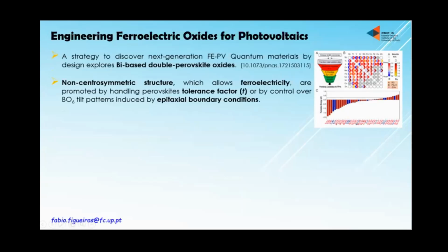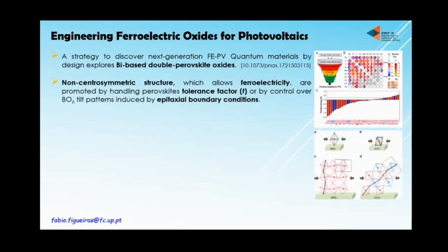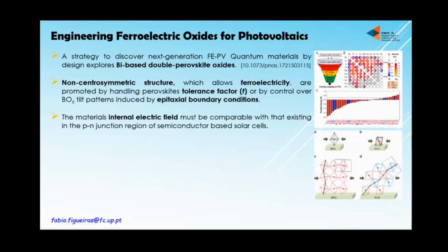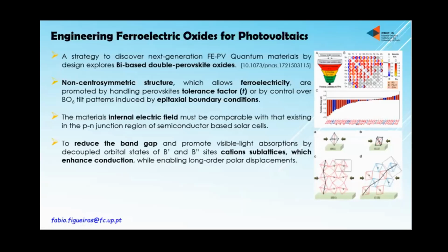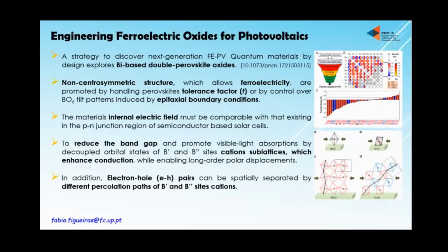Bismuth-based double perovskite oxides. We have a non-centrosymmetric structure that promotes ferroelectricity, and the difference between two ions on the B site, a difference in chemical element, being ionic, will generate two sublattices which will have different conduction and lower the band gap. At present, very good results with bismuth, iron, chromium oxides have reached photovoltaic pre-prototypes reaching 8.1% efficiency.